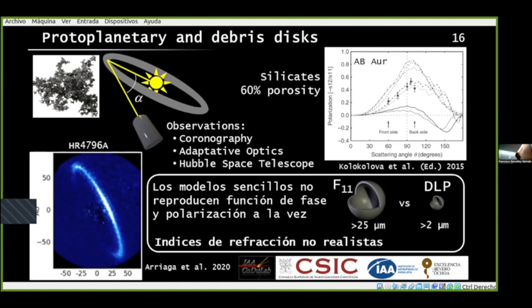In this case, if you use the hollow sphere method for fitting simultaneously the phase function and the degree of linear polarization of this disk, if you fit the F11, you get particles which are larger than 25 microns. If you fit the degree of linear polarization, you get particles larger than 2 microns. So there's one order of magnitude difference there. And also in either case, the refractive indices that you get are not realistic.